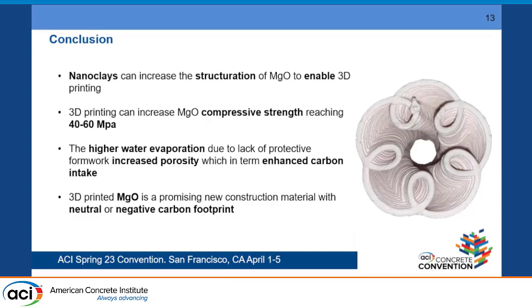So with this, I can conclude with the main summaries of my talk. First of all, nanoclays were successful in increasing the structuration rate and enabling the 3D printing of this material. This is a very tough material to print. We can't rely on accelerated hardening like we would in typical Portland cement, simply because it's hardened straight when it's hydrated and is still too weak. So in this case, the static yield stress is the one thing carrying all the 3D printing performance. And when we can 3D print it, we can reach compressive strengths between 40 to 60 megapascal, which is sufficient to use it as a structural material.